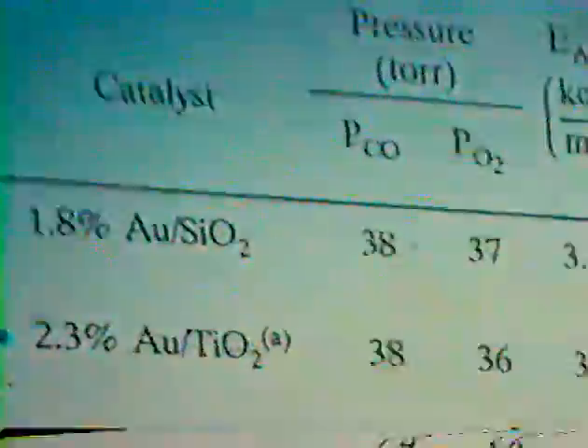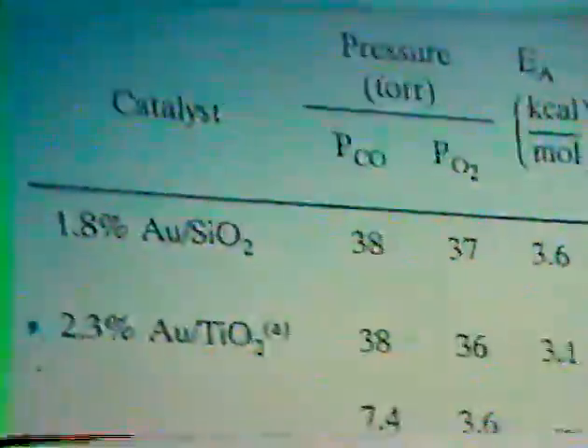And the lifetime of those lasers, which are used for meteorological studies and weather forecasting, is determined by the degradation of the CO2. And that's the requirement that NASA has for a low-temperature CO oxidation catalyst for recombination to maintain the lifetime of these orbiting CO2 lasers. Under those conditions, these are fairly representative of what might exist in that particular system.